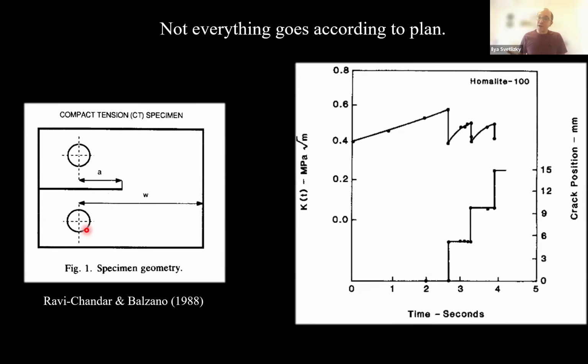In the late 80s, Ravi-Chandar and Balzano took a sample under tension and applied displacement at the two ends of the sample. They were able to measure the stress intensity factor, this is the top, and the crack position on the bottom. As time goes up, the stress intensity increases, reaches some critical value, and then drops at the time that the crack jumps. For the next jump, you need to keep on increasing the stress intensity factor.